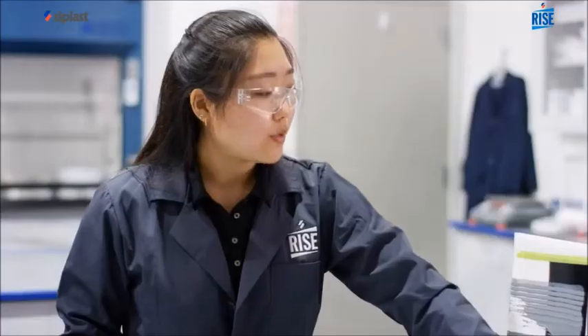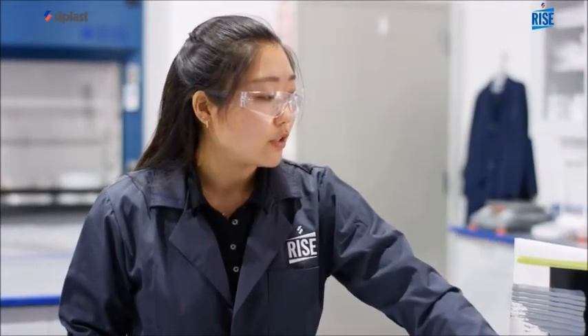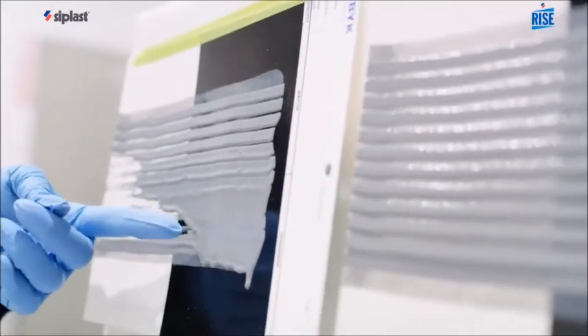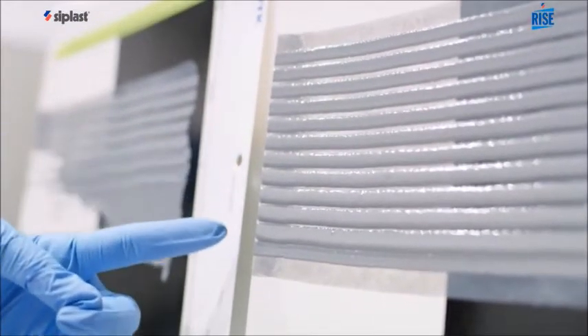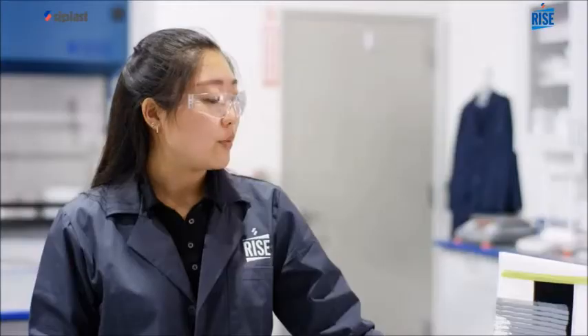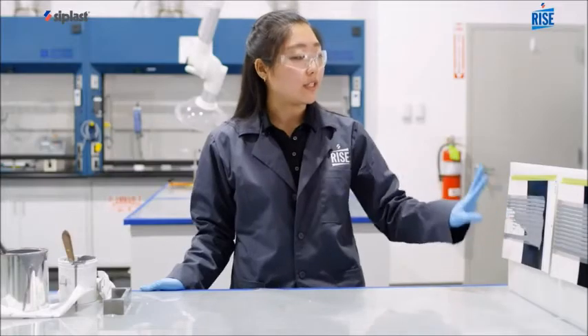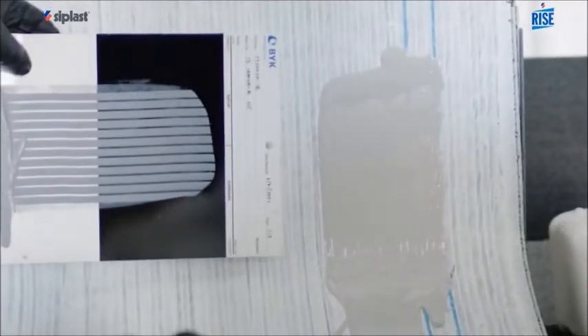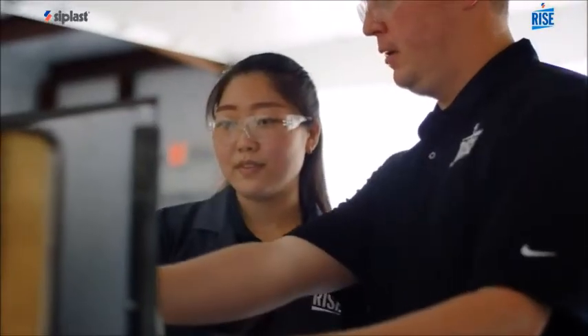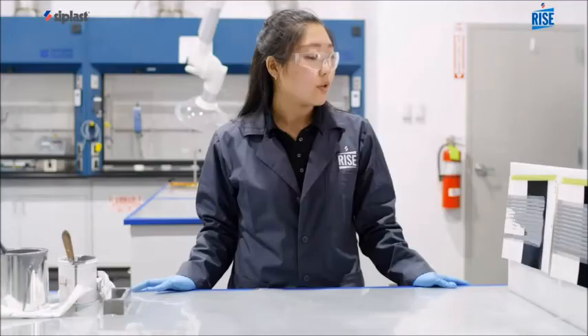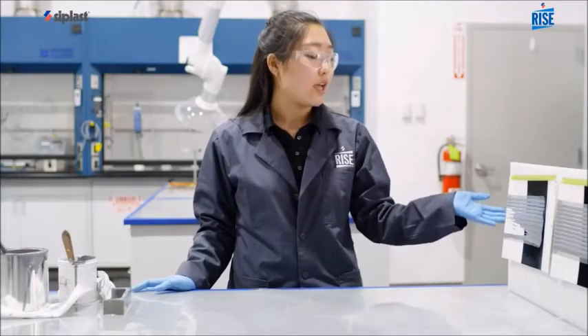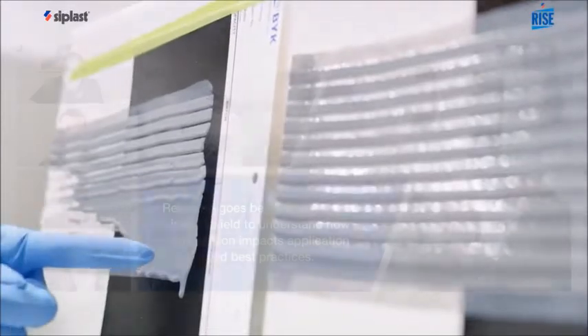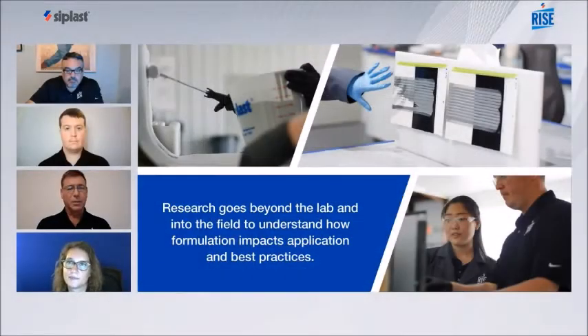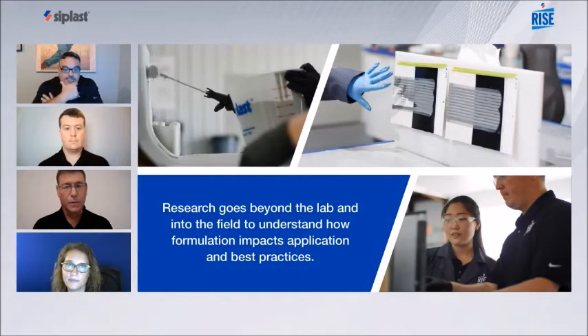So as you can see, we're comparing two different rheology modifiers here, and we see that one on the right serves its purpose better. We would not want to see a flow like this on the left. This is what we see in the outside application when we try applying it on the vertical surfaces. For the ones we apply horizontally, it's okay if they flow at a certain thickness. So as you can see, Min's demonstrating some of the characteristics you would look for in the field.